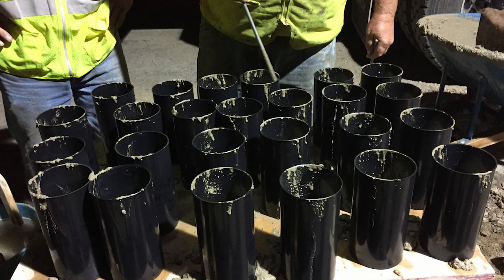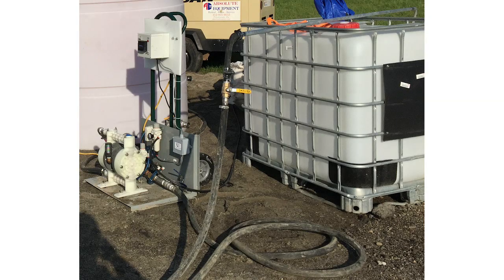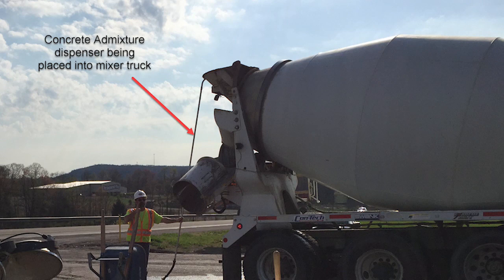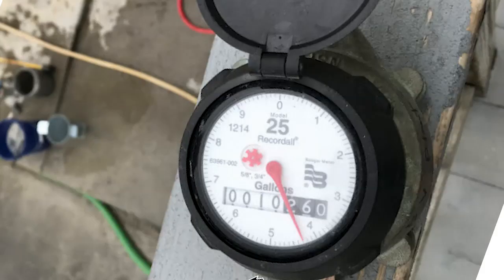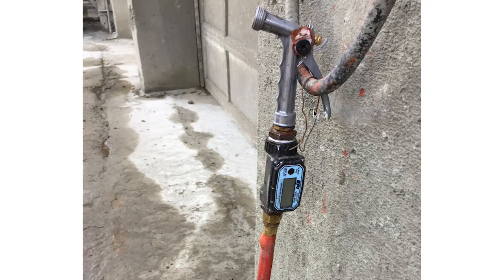If one or more truckloads of cement concrete exceed the slump target range, make additional quality control and acceptance cylinders from each load. Use the lowest compressive strength cylinder result for acceptance of the lot. The adjustment of slump may be allowed through the addition of additional water reducer admixture at the job site, provided a comprehensive procedure detailed in the quality control plan has been submitted and approved for this purpose. The addition of water to adjust for slump, when permitted, must be from a metered system.